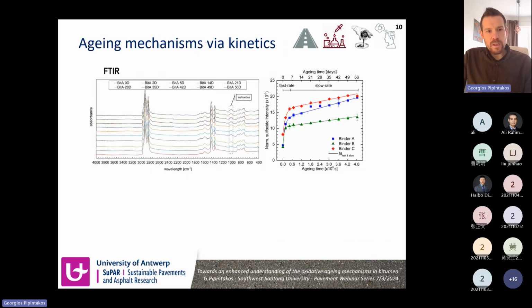Now, jumping to the results, as I mentioned, FTIR was studied in all the time intervals from 0 to 56 days, as you can see on the top left. And from these FTIR spectra, we isolated the sulfoxide area, and this was calculated and plotted on the right. You can observe that all three bitumens, A, B, and C, showed an initial rapid increase until approximately 7 days, which is considered the fast rate phase, followed by an almost constant slope, which is the slow rate phase of these binders.